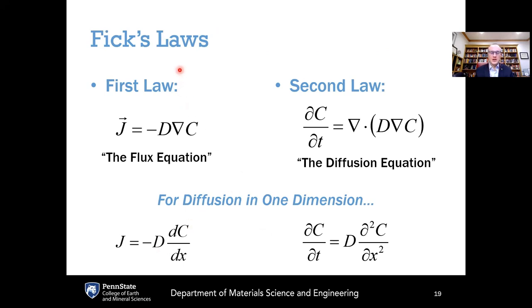So for Fick's laws of diffusion, we have the first law. The first law is also known as the flux equation. So if somebody working on diffusion just says the flux equation, what they mean is Fick's first law. This is what takes our scalar here, concentration. You take the gradient of that to give you a vector, multiply by minus the diffusion coefficient, and that gives you the flux vector. Fick's second law is also known as the diffusion equation. So if somebody says the diffusion equation, what they mean is Fick's second law of diffusion. This takes the negative result here of this flux, applies the divergence operator to it, and then gives you the time rate of change of the concentration.